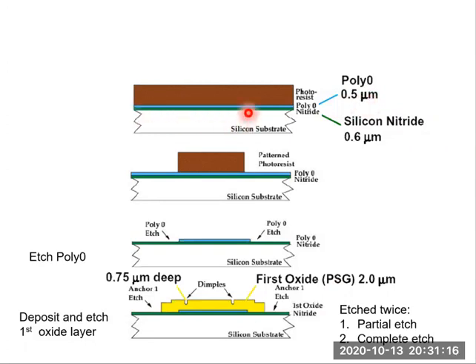Then spin coat a photoresist layer. Pattern this photoresist using photolithography. Then etch poly 0, the first polysilicon layer, using this photoresist as a mask. Okay, so the pattern is transferred from the photoresist to poly 0. We call this a poly 0 etch.